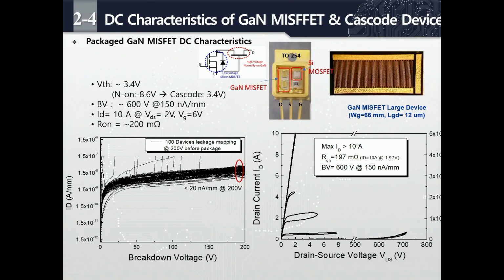After the device is fabricated, we normally test 100 or 200 devices to check the leakage mapping. Sometimes early breakdown happens, but most of the devices survive, and they also have very low leakage current levels, around 20 nanoamperes at 200 volts.